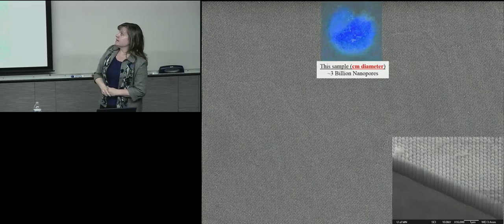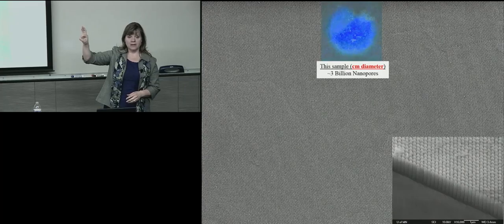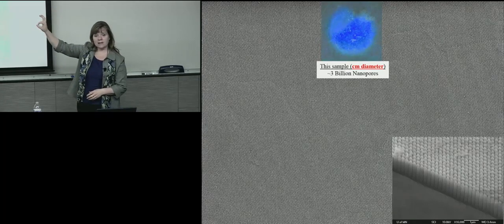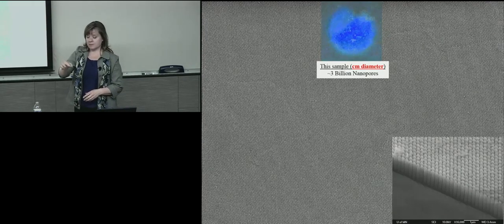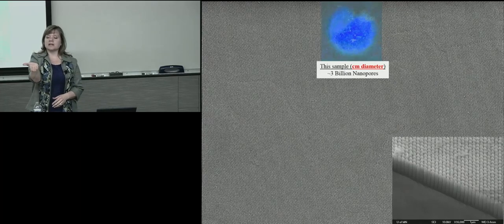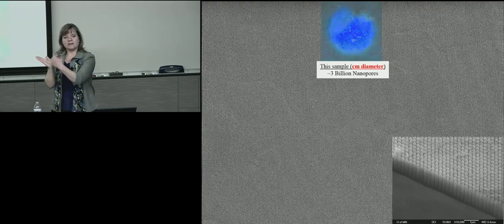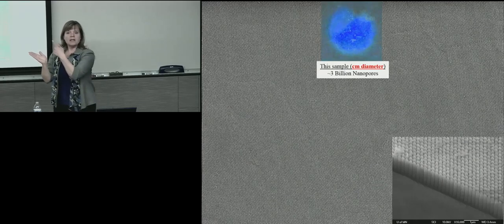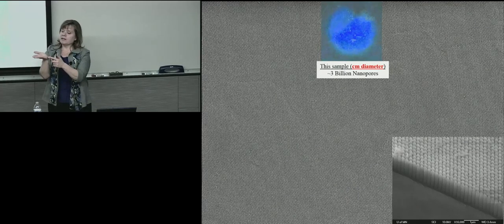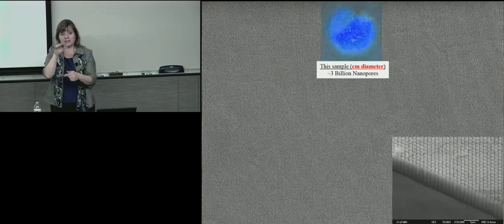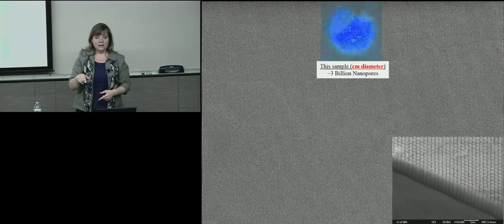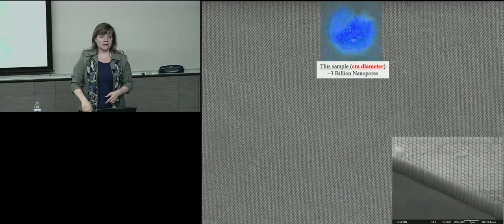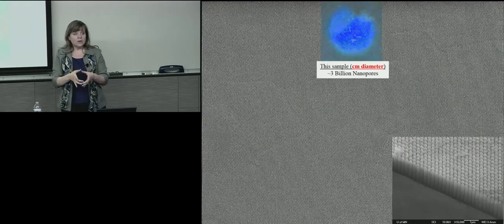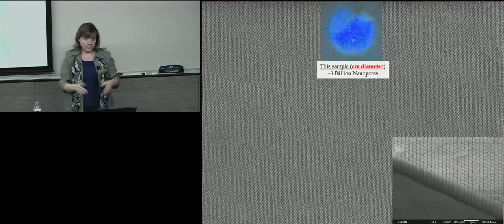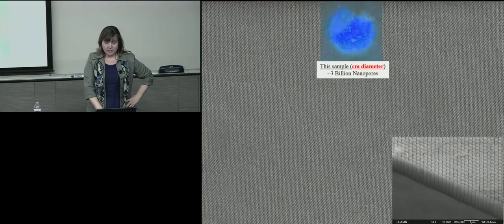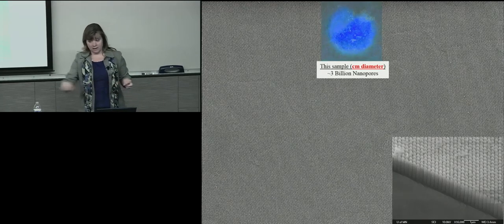And here what you see is just a 1 centimeter. So that blue is 1 centimeter in diameter. And the only reason it's blue is because we took our sample like this and we look at it until we see a diffraction of the light. And the spacing gives us blue. And as we rotate our sample, we see that blue flash 6 times because it's hexagonal. But otherwise, it's gray, like the outside of the blue, because they're just nanowires. So we know they are perfectly ordered, or we wouldn't see blue. And that's a centimeter in diameter, which means 3 billion nanopores all lined up perfectly.